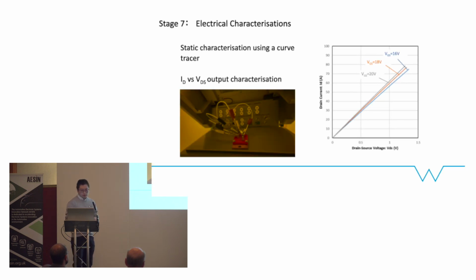So now it's stage 7, electrical characterization. Firstly, we did static characterization using a curve tracer. This is our power module under test. Among all the tests, the output characteristics is what we are most interested in, which is just the drain current against the drain-source voltage. This is a result at different gate voltages. As expected, when you have higher gate voltages, you will have lower on-state resistance. So the line will be shifted up a bit. For this particular power module, when you have about 100 amps, you will have about 1.5 volt drop across the drain and source, which matches the datasheet of the die we used inside the power module. So we're happy about this.